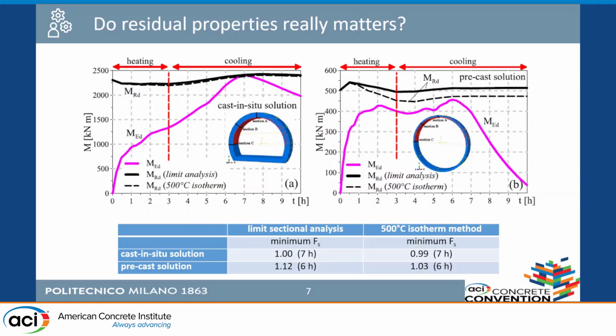And what you observed is that in the plot you see that in the first 3 hours we have the heating phase. After the vertical red dashed line, we have the cooling phase. And in these cases, with both structural technologies, we have that the least value of the safety factor was reached far after the maximum temperature reached during the fire. That was after 3 hours, so during the cooling phase.